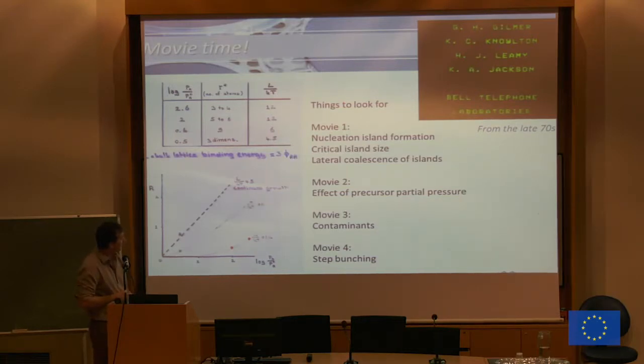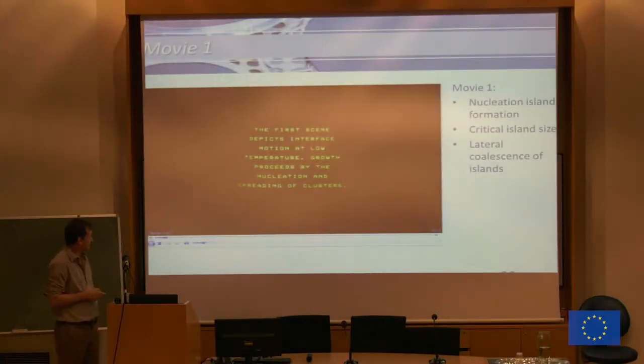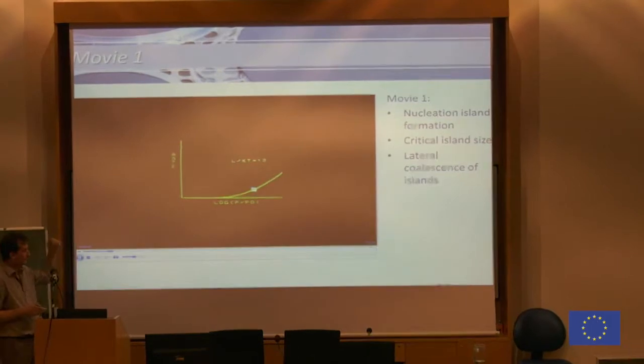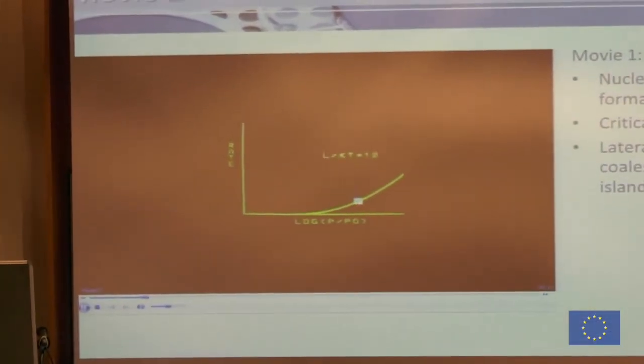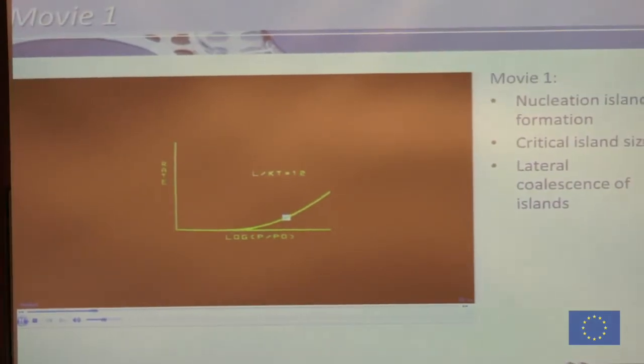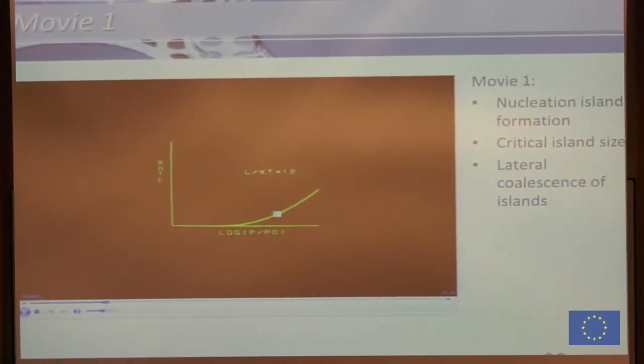So we start with the first, and one of the things I want you to look at is we will have nucleation, so we will have islands forming on the surface. There is such a thing as a critical dimension for such an island so that it maintains. And so what I want you to do is pick out one of these islands that will be formed and try to see how it behaves in practice. So this should start by itself. So we have growth on a very flat crystal, and you will see the atoms impinging. So we are working here on this particular oversaturation point. And then we will see how the atoms behave. It should start any time now.